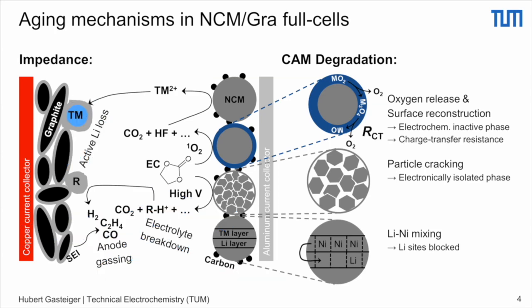If we look at this, what can we measure? When we look at the formation of a surface reconstructed phase, we expect an increase in the charge transfer resistance, which in principle one would be able to measure. In the case of particle cracking, what we expect is an increase of the electrochemically active surface area, meaning the electrolyte wetted surface area. So we would expect an increase in the capacitance, and a little drawback is that the charge transfer resistance also would go up a little bit. And in case of lithium nickel mixing, of course, we expect a slower lithium diffusion coefficient in the active material, in the bulk of the material.